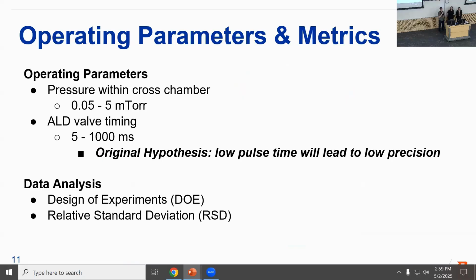So our whole process is based on these 2 operating parameters and how they affect the gas dosage. We have the pressure within the cross chamber, and we varied that between 0.05 and 5 millitorr. This was just based on the Baratron pressure sensor. This is the range that worked with it on top of that cross chamber. And we also have the ALD valve timing, or the pulse time, and we varied that between 5 and 1,000 milliseconds. We went down to 5 milliseconds because that's the operating limit for the ALD valve we used. It can only open and close so quickly.